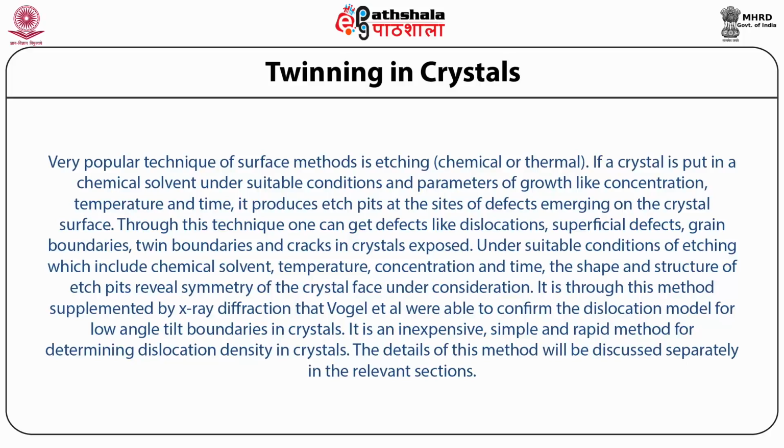If a crystal is put in a chemical solvent under suitable conditions and parameters of growth like concentration, temperature and time, it produces etch pits at the sites of defects emerging on the crystal surface. Through this technique, one can get defects like dislocations, superficial defects, grain boundaries, twin boundaries, and cracks in crystals exposed.